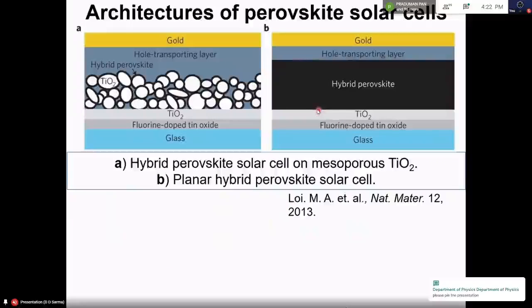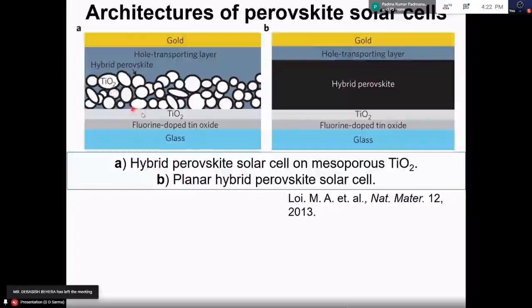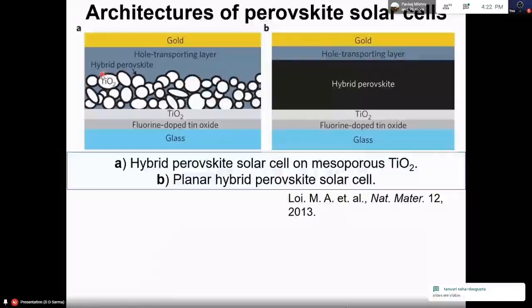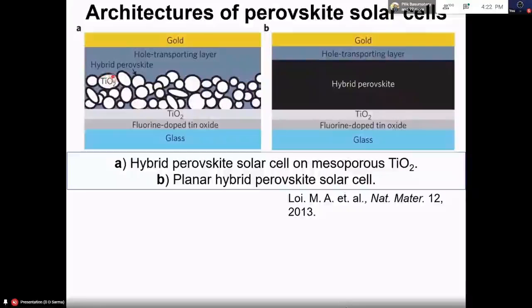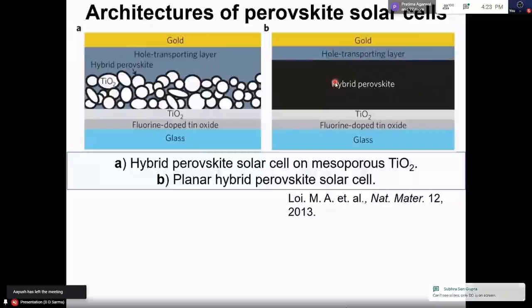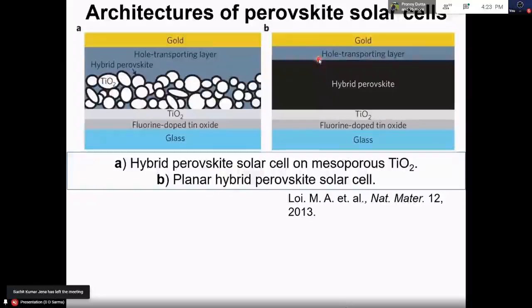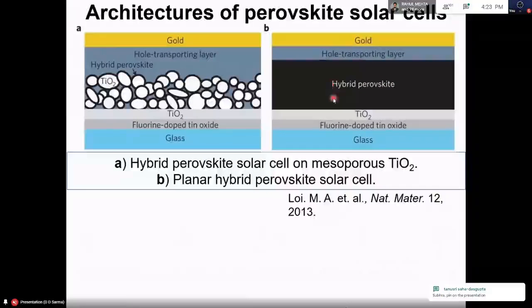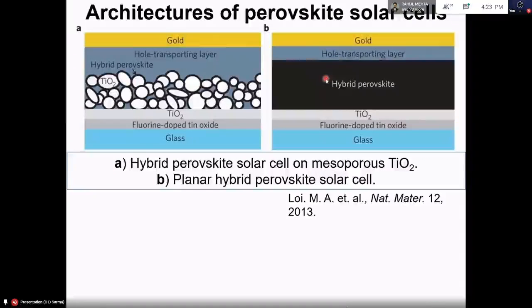And in fact, this was very quickly shown: not only electron, you could make a structure. This is the usual structure that one would make for the dye-sensitized solar cell-like structure, where you have TiO2 for electron transport. This black layer is the dye, which is this methylammonium lead halide, and then the electron will go into TiO2, and this TiO2 network will connect the electron and bring it out from here. And the hole will go out that way. But instead of that, what this particular paper showed is that you can have a complete layer of this hybrid perovskite, such that not only the electron transport but the hole transport also will take place through this layer. And they found high enough efficiency in this to point out that this is fundamentally different from the technology of the dye-sensitized solar cell shown over here.